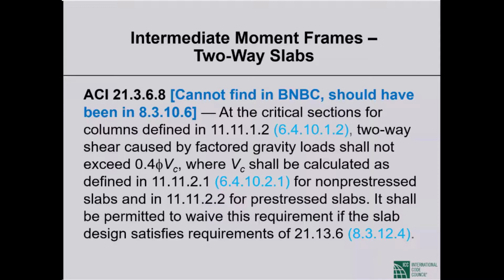So this is a very important requirement of ACI 318 that, to my surprise, I did not find in BNBC. I checked with Dr. Rakib, and I can tell you that it is not there, and if it were there, it would have been in section 8.3.10.6. This is a pretty glaring omission, and all I can say is something needs to happen to reinstate it. I don't know what mechanism is available. Okay, now to say that shear due to gravity shall be lower than 40% phi times V sub C is easy, but in design that is a severe restriction. It will limit what we can do with flat plates, what spans we can use, what loads we can take.